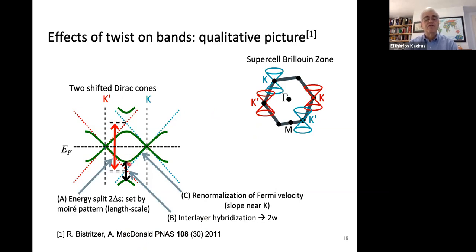There are three effects of the twist. First of all, these two Dirac cones, the blue and the red one, intersect at these points. And the distance between these points where they intersect, which is called 2 times delta E, this distance in energy, the vertical axis here is energy, is set by the Moiré pattern, the length scale of the Moiré pattern. The second effect is that the degeneracies at these points of intersection will be split when you turn on the interaction between layers. And this amount of splitting will depend on the interaction between layers. And this is referred to as the 2W energy scale. And finally, because of this splitting, the bands will be bent, and the Fermi velocity associated with the slope of these bands will change. So there's a renormalization of the Fermi velocity because of the bending of the bands.